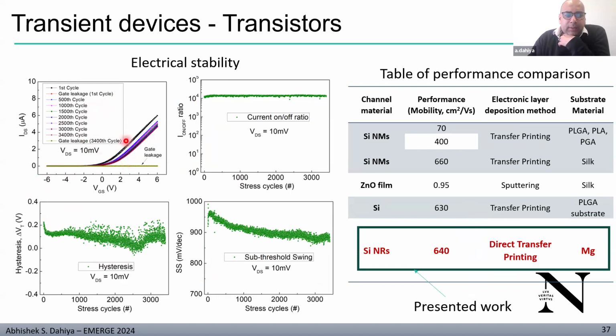This is the long-term cycle stability test we have done. So this can degrade, yes, but till its life, the device should be stable. So this is an attempt to test the stability of these devices. We have done up to 3,400 cycles forward and reverse. Very little hysteresis we found, and as you can see, the performance remains quite intact. So these are the expected parameters, on-off ratio, SS, and hysteresis, up to all these cycles, and they are stable during the operation of these devices.